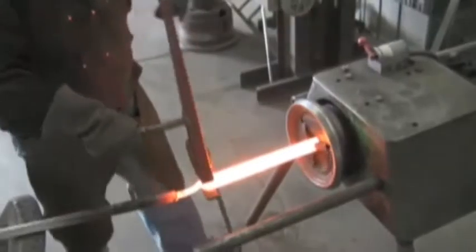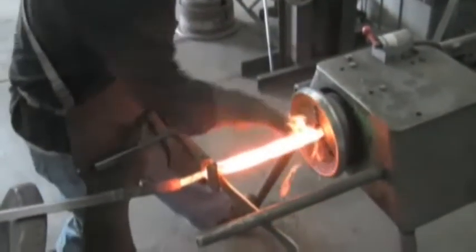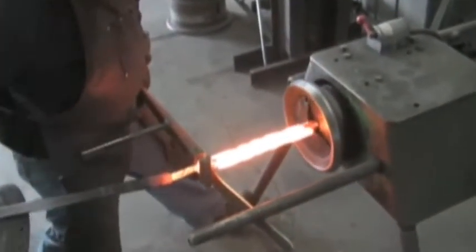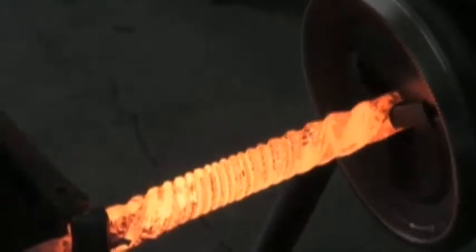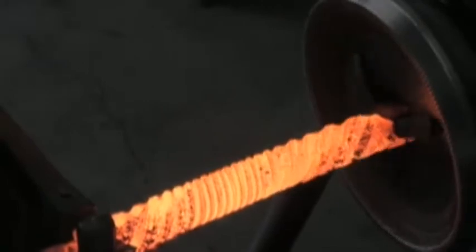Using an auto twisting machine, he twists the Silver Stag billet into a ribbon twist pattern bar. The bar is then forged out into blade stock size, hand ground, and the final blades are heat treated in molten salts to a 58 Rockwell hardness.